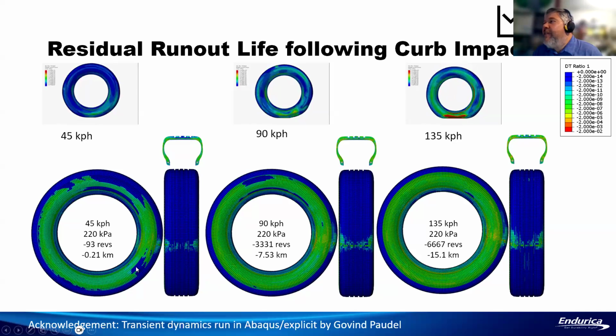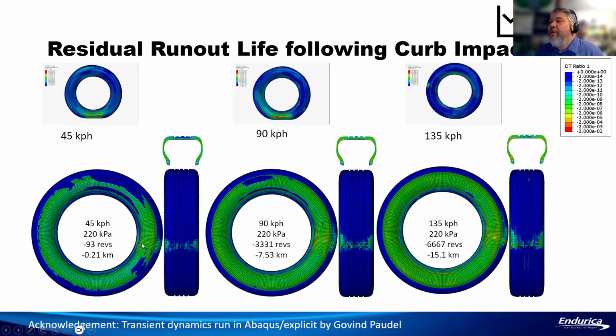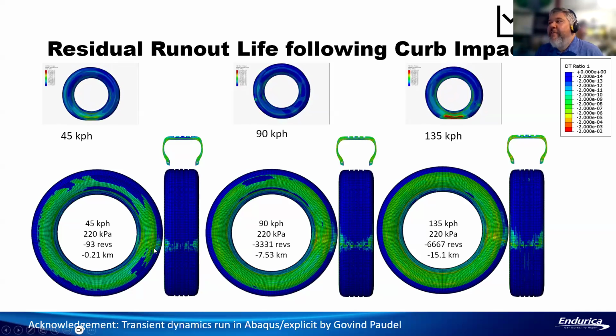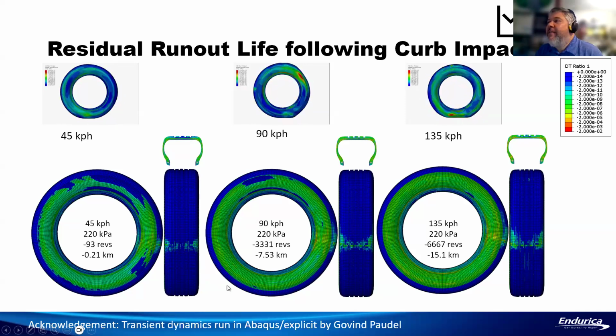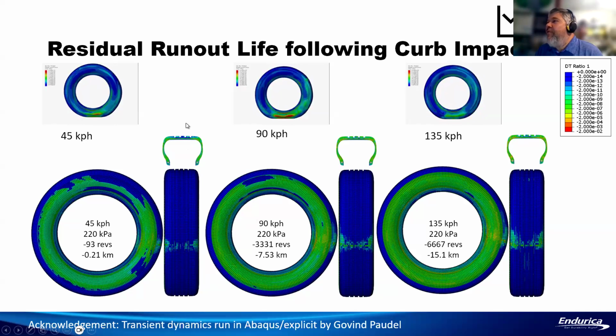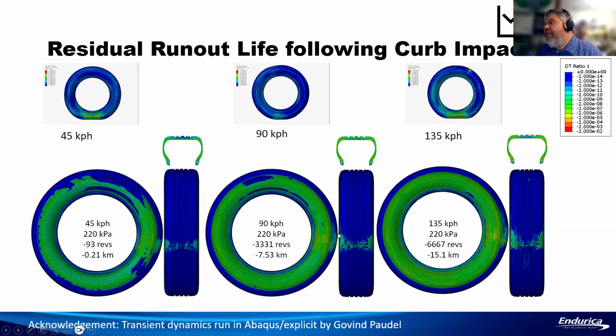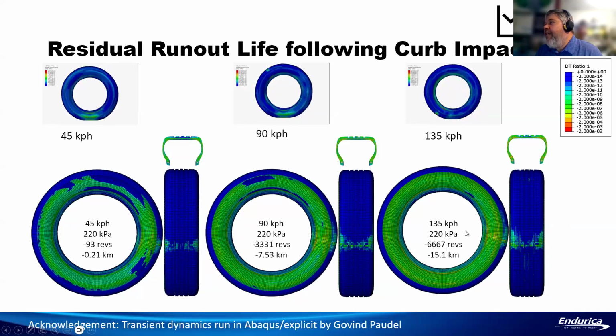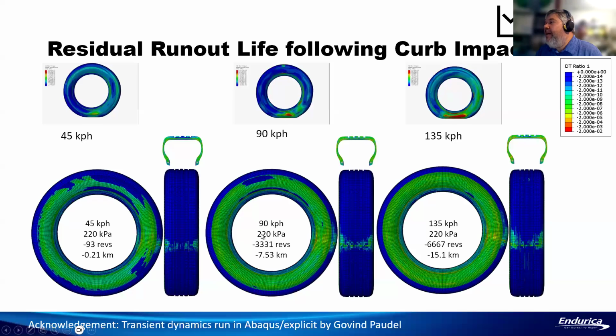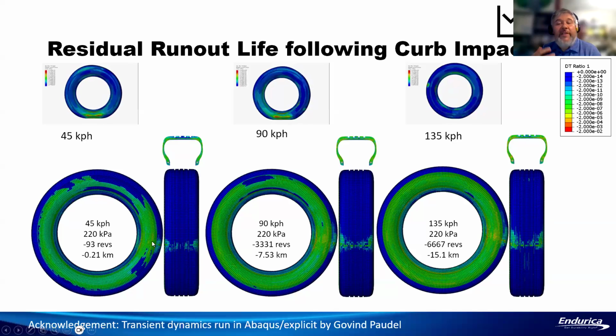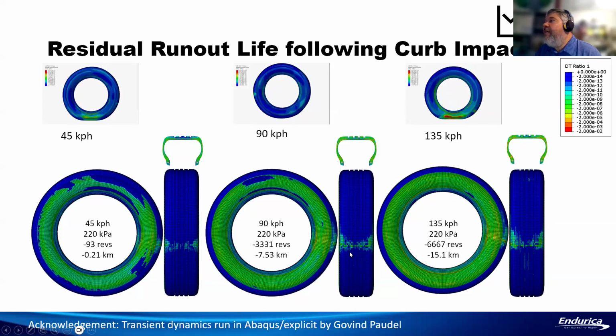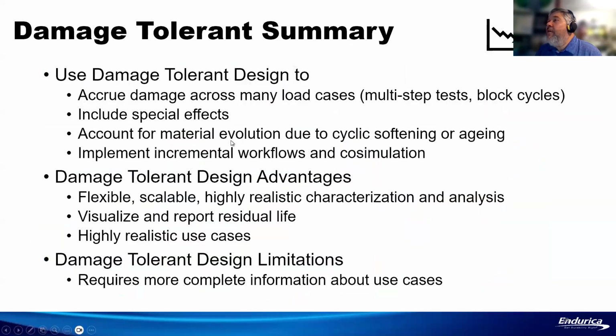And what you're looking at in these contour plots is the percentage change in the residual life relative to the case where you don't have the impact. And you can see that when you do the impact, it produces a bruise on the tire. And you can see where most of the damage in the tire is happening. If you peel this away, you find out that this does some damage to the belt structure of the tire. So those are some examples of damage tolerant analysis.